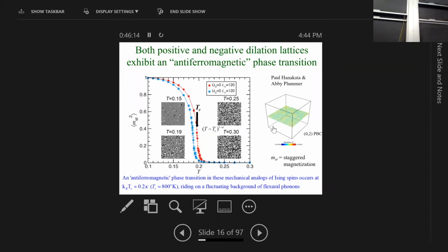Yeah, so if this two-dimensional film is an amorphous material, does it make it a spin glass? Oh, if it were amorphous, there's all sorts of interesting spin glass issues. And even if it's just a triangular lattice of these puckers, for example, there's geometrical frustration, which you might well remember. So if I have a triangular lattice, now this one is buckled up, then this wants to buckle down, then this one is getting confusing mixed signals. And so even on the level of a triangular lattice, there can be frustration. And if you have randomly located puckers, there could indeed be non-trivial spin glass stuff. So we stayed away from it just because we wanted to do something that was a little more amenable to our understanding. But that would be a fascinating thing.